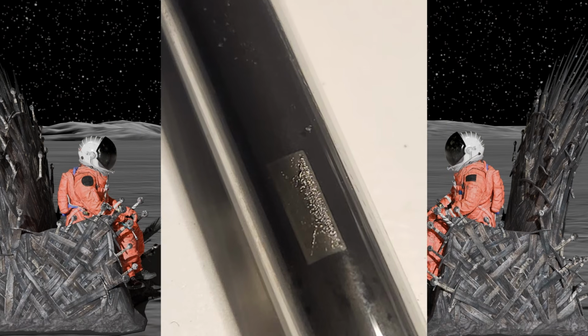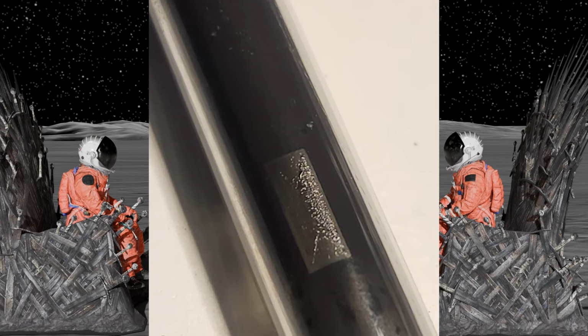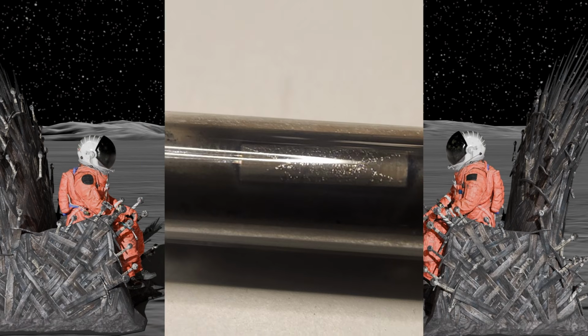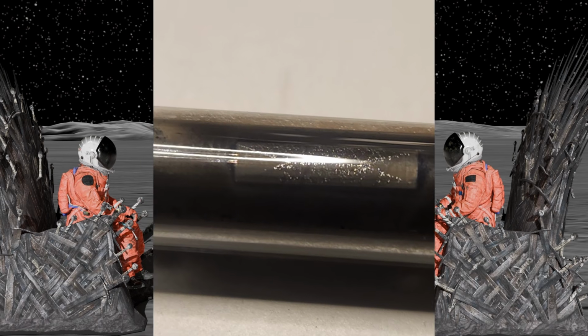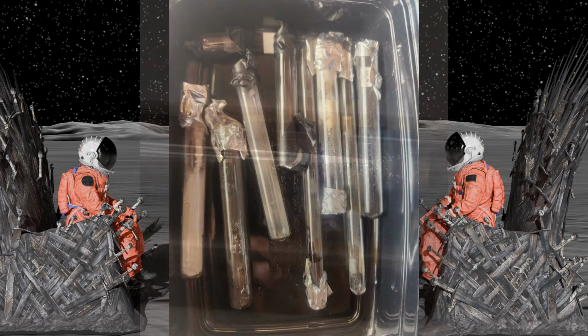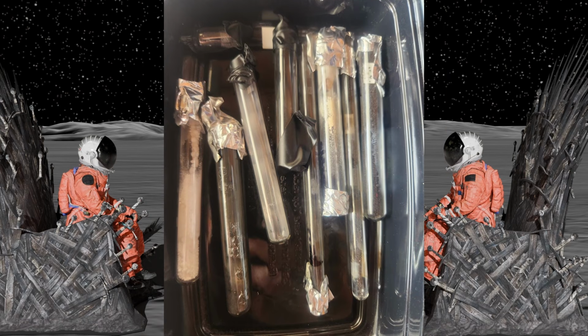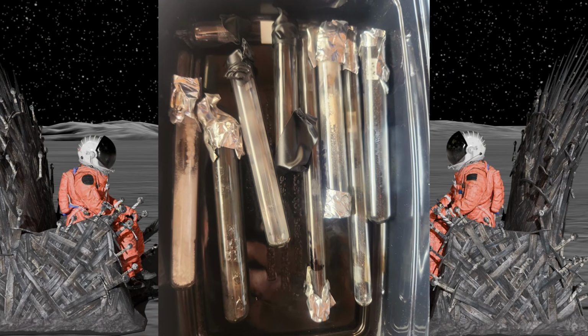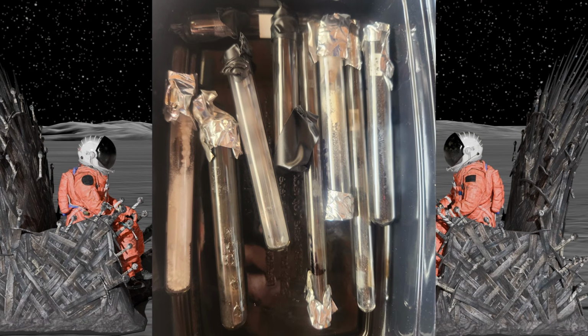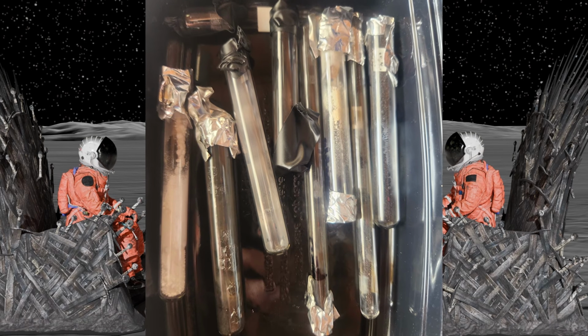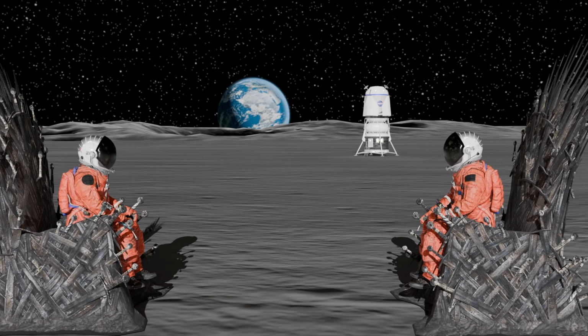And just to clarify, you went through and you tested on individual oxides to figure out the optimal laser settings to reduce that specific oxide. So you had a whole bunch of different test tubes, and each one of them you put the pure oxide, like calcium oxide or titanium oxide that we would find in the regolith, and then you figured out what the settings were to reduce that. And so by doing this, you built up a settings library essentially for your laser, right?